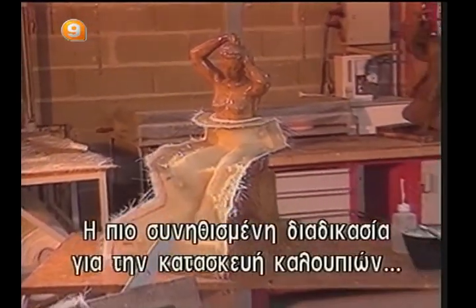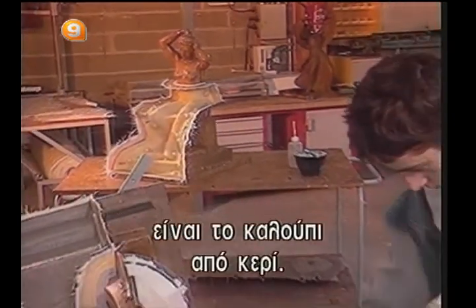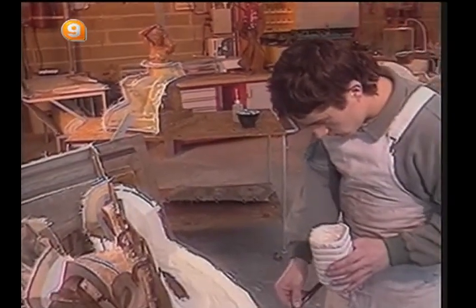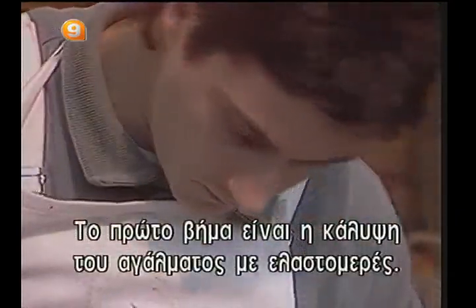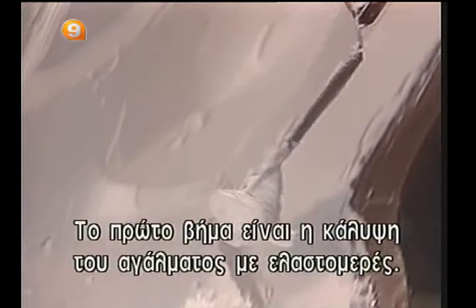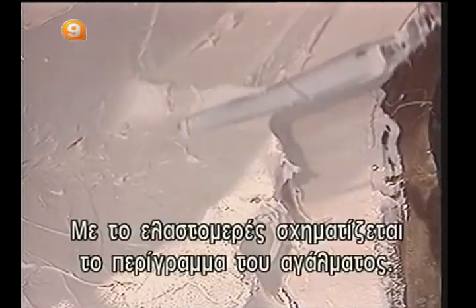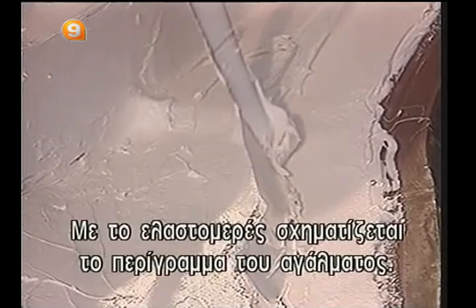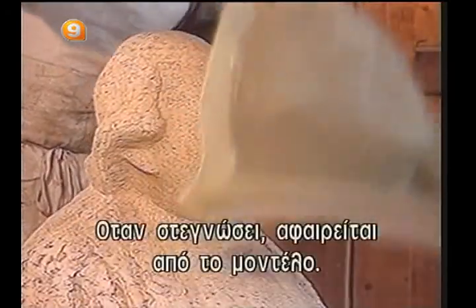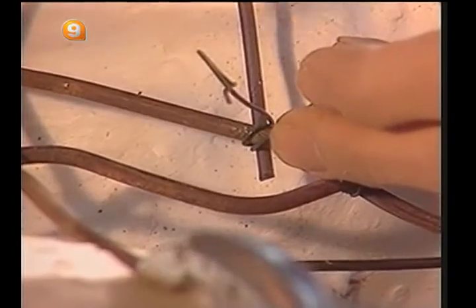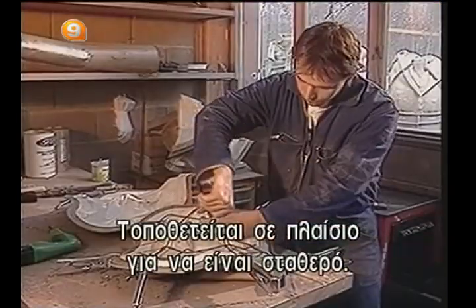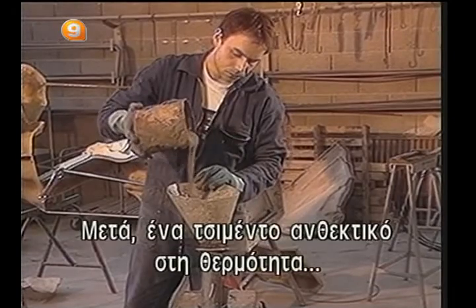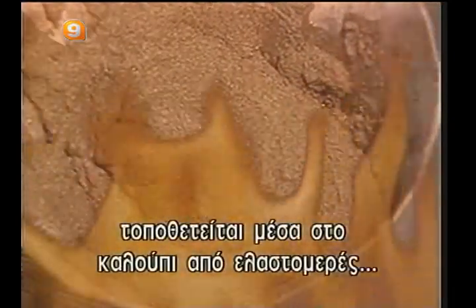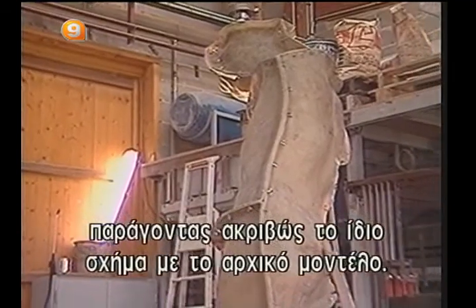The most common process for casting a bronze statue is called lost wax casting. The first step consists of covering the sculpture with a liquid rubber called elastomer. In a sense, the elastomer forms an impression of the sculpture. When dry, it is removed from the model and encased in a frame to keep it in place. Next, a heat-resistant cement is poured into the elastomer mold. This core reproduces the exact shape of the sculpture.